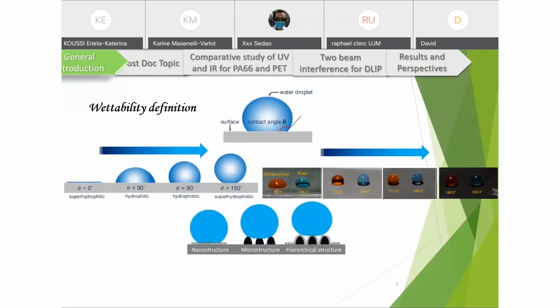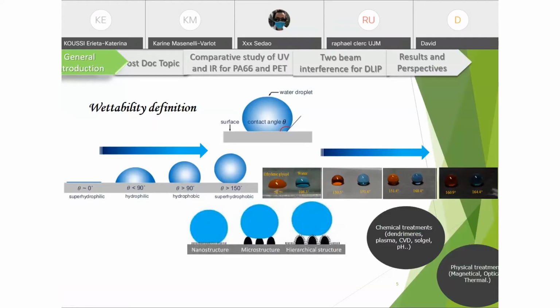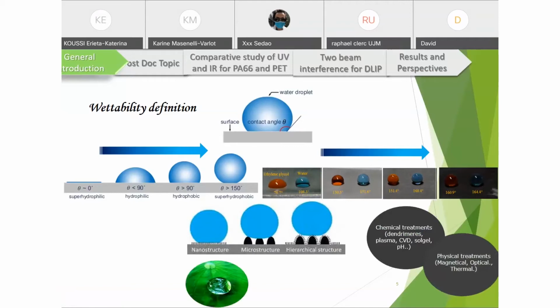So, to enhance the hydrophobicity, we have to pattern the surface properly and texture it at the nanoscale or with a micro and nano combination scale to become a hierarchical structure. And this is really a challenge. To realize such a complex surface engineering, we can pass through physical treatments, mostly for nanopatterning, or chemical treatments. But there is also the option to combine both physical and chemical treatments. Worth mentioning that a surface can be engineered to be superhydrophobic, and further treatments can potentially allow oleophobicity. The opposite effect is not applicable, and an oleophobic surface is necessarily hydrophobic.